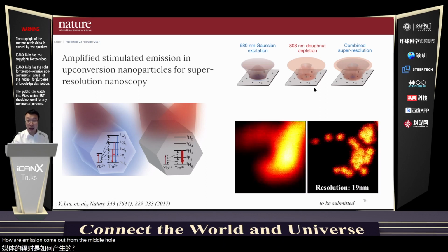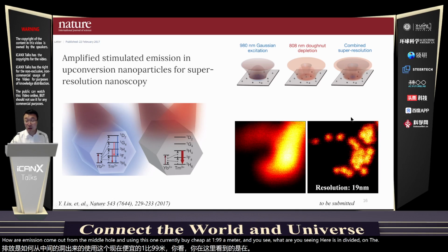By using this concept, we can directly adopt STED technology to do super-resolution. You use one laser for the excitation, and you use another donut beam as an eraser, just cleaning up the emission surrounding the hole, so emission comes out only from the middle. Using this, we currently achieved 19 nanometers. What you're seeing here is an individual nanoparticle, and this is inside a single cell.